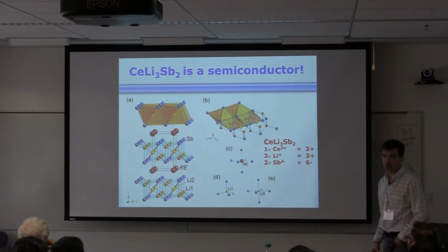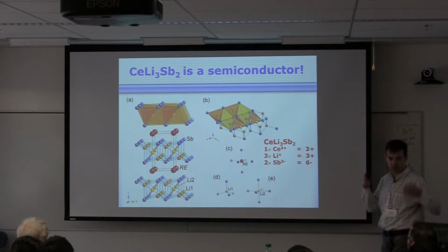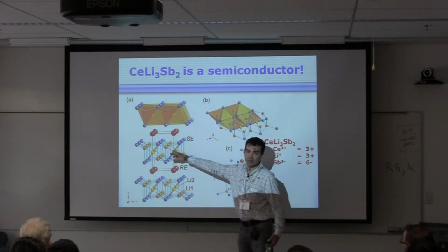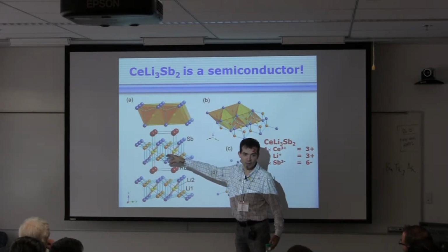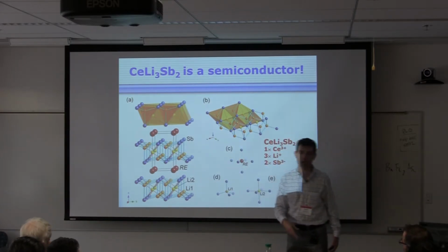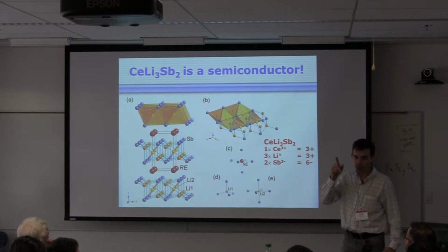You really have to have a good crystal, and a really good eye. And when you do, then you identify the electron density sitting here in the middle of that layer. You put lithium there, you refine it, and your R value goes from 2.1 to 2.0.